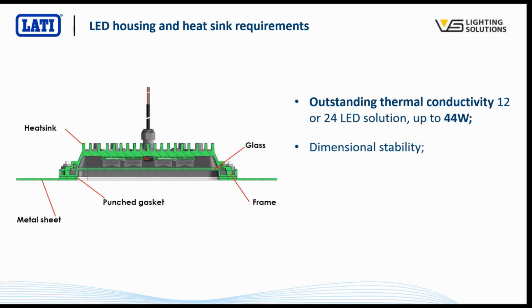We must have dimensional stability. So for the heat sink to work effectively, it has got to be in contact with the components that are generating the heat. We don't want an air gap between those two things. So dimensional stability is important to make sure that we maintain that good physical contact. We need an absolutely flat molding. Otherwise, we're either going to have an air gap, or we're going to have to start using thermal interface materials, which adds an extra process, adds extra costs to the production of these units.